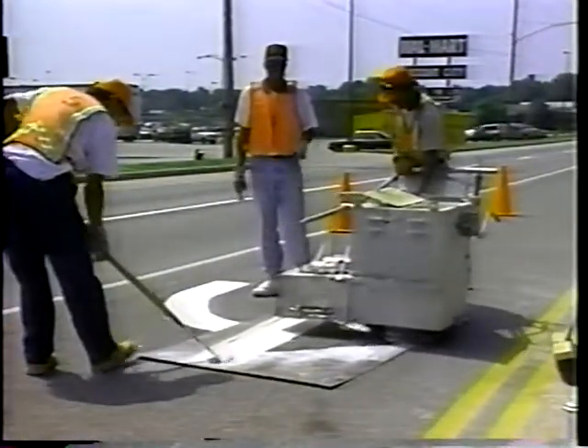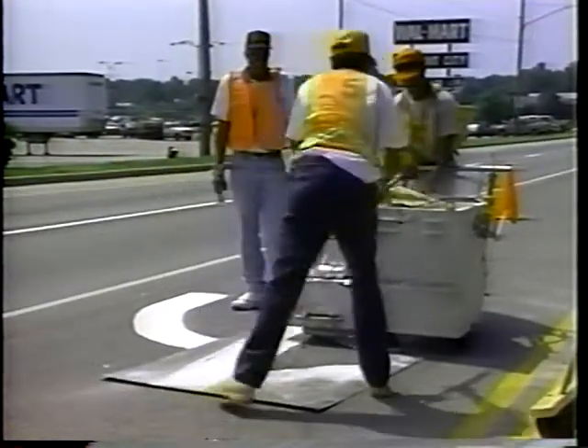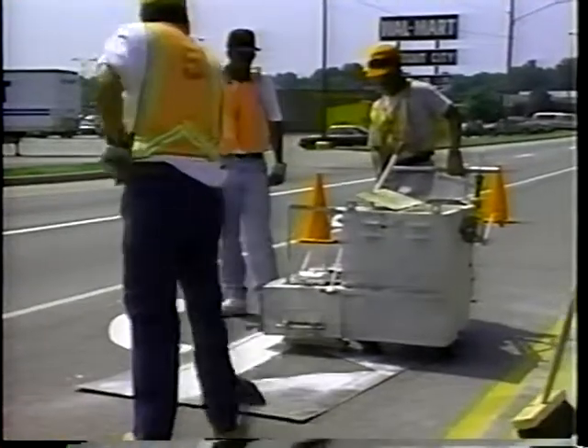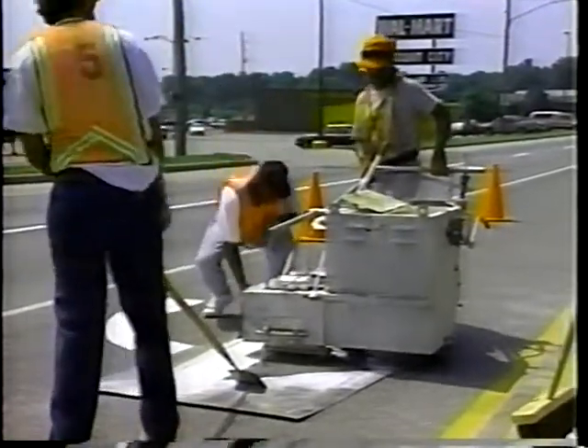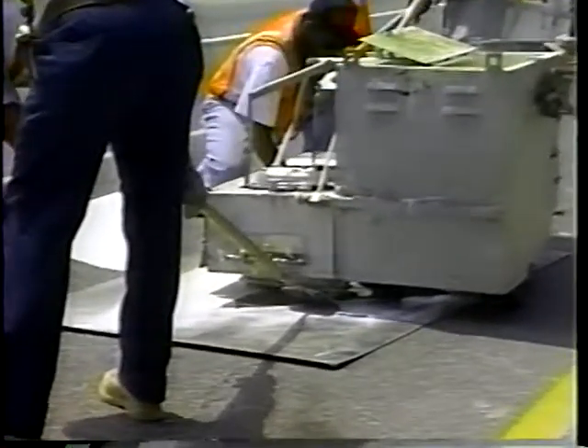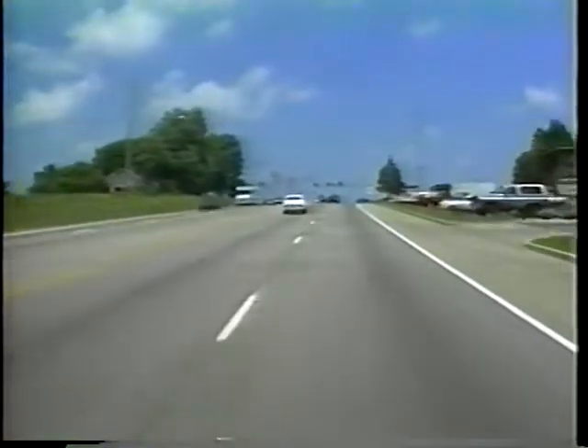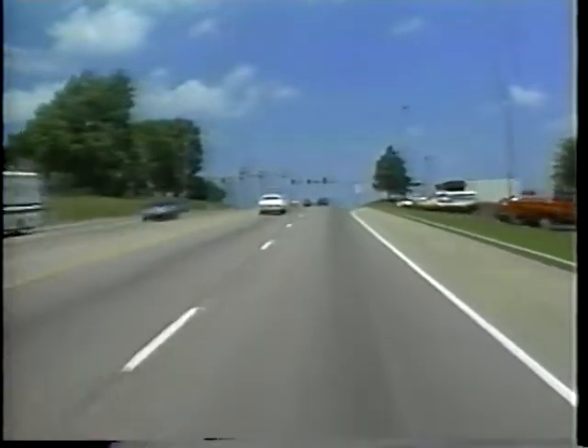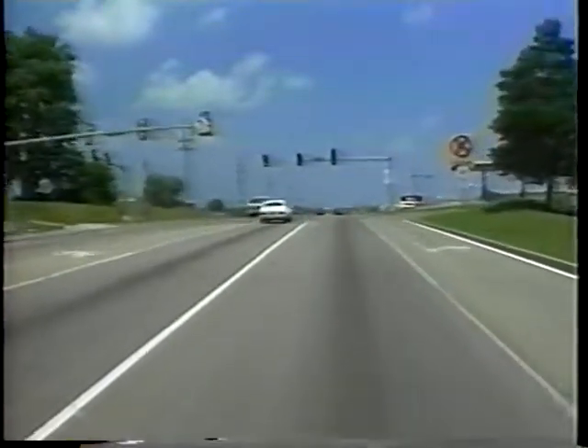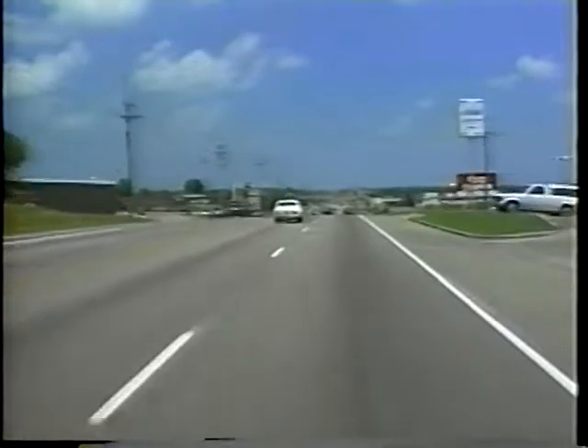Pavement marking materials should not be applied to dirty pavement surfaces. Laboratory tests have indicated that cleaning the surface of dirt, sand, grit, gravel, and other foreign materials prior to application substantially improves adhesion. New Portland cement concrete pavements generally have a film of curing compound on the pavement surface. This film must be removed prior to application of the marking materials. The width of removal should be the width of the markings plus 1 or 2 inches.